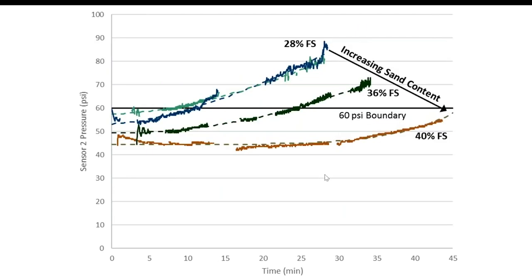We can do things like sand content. We all know that sand impacts pumping pressures, but look at this. As you increase the fine sand, not all sand, the fine sand, in the mixture, the pumping pressures go down. It gets easier to pump, not harder. You might say, wow, how did you figure this out? Well, iterations over and over and over again. And don't worry, we're going to make this really simple for you coming up.